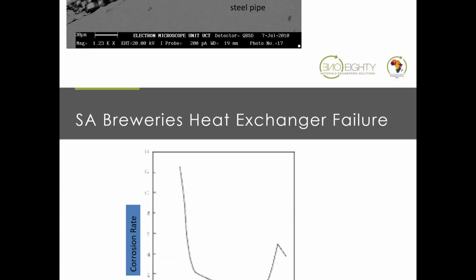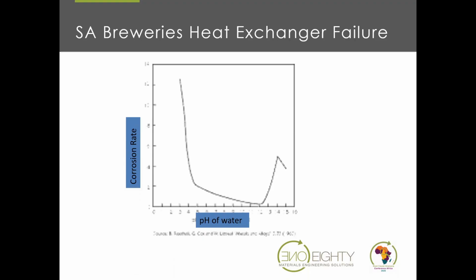Okay, so then the manufacturer was determined to prove that it was the brewery's fault. They said, no, forget about that. The reason this all happened is that the ammonia leaked for some other reason, got into the water, changed the pH of the water all the way up to 14, and that would have taken the galvanizing off in 2 minutes. So I thought, well, this is really ridiculous.